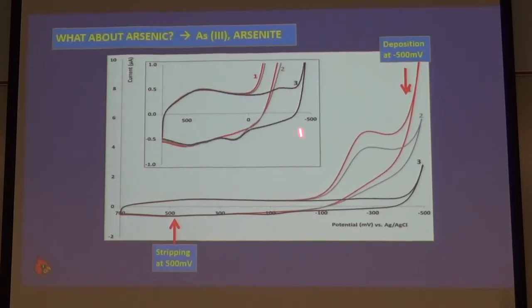If we take all the oxygen out of the solution, we deaerate the solution ahead of time, we get rid of the oxygen, and now, if you have an imagination, you can see a little wave out there that corresponds to the arsenic reduction. Arsenic's not very concentrated in this solution. And if you go back, you can see a little oxidation corresponding to the stripping of the arsenic. If we blow that up, there's the arsenic reduction.